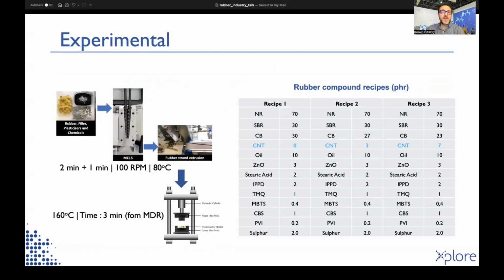These are the recipes that we prepared. The matrix was based on an NR-SBR blend, which is reinforced with 30 PHR carbon black. The carbon nanotube content was changed from 0 to 3 and 7 PHR by replacing the corresponding amount of carbon black. The rest of the recipe was kept constant.